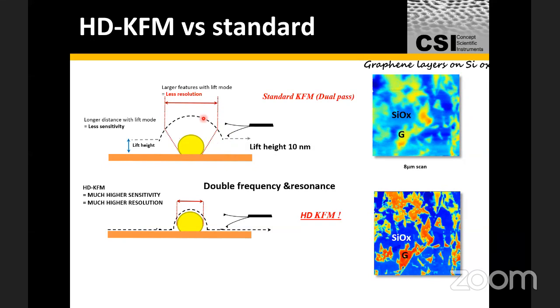Unfortunately, you have to lift your tip a bit, and it's that lifting of the tip that results in the haziness or the lack of resolution. Which at the time, of course, was great resolution, but things have improved since then, and we are able to come from where we were in 2010, for example, to making these sort of measurements to coming down to here, where you can clearly see the difference in clarity here.